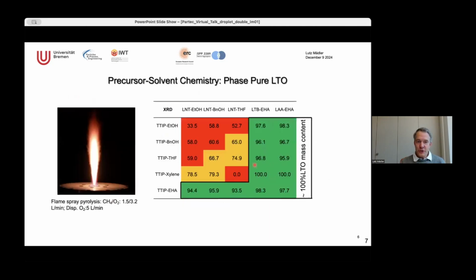So what I just showed you was this combination here with 100%. So we only get a few of them that have 100% phase purity, and some others are not really getting 100% phase purity. In some cases, you only get 70% or 60 or even 0% of phase purity of that mixed metal oxide, lithium titanate. And the question is, why is that? And this is what my talk is about today.